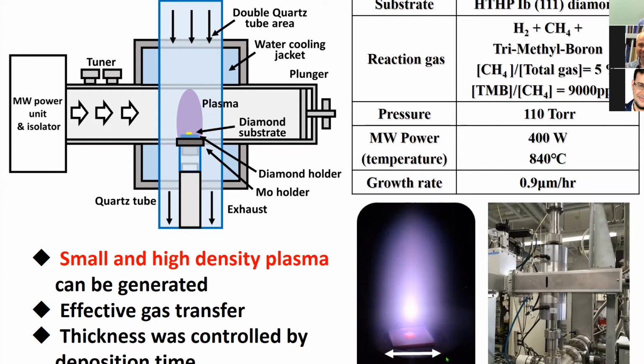For example, this is just 1 centimeter, a very small region, where the plasma ignites, and the center plasma is just on the substrate. So it's a very focused region, and we get very high dense plasma. The pressure is just several times lower than atmospheric pressure, but it's enough to get superconducting diamond or nice material. Without boron, we get nice pure diamond, but this machine is good for doping.